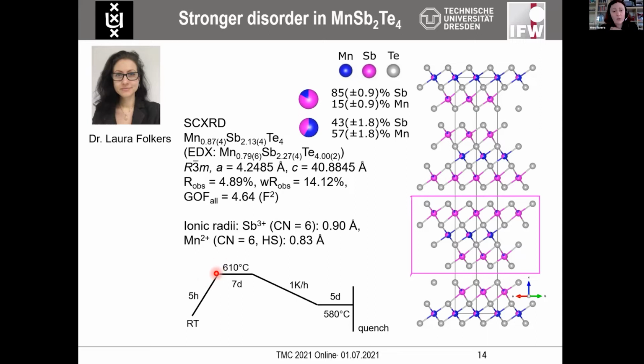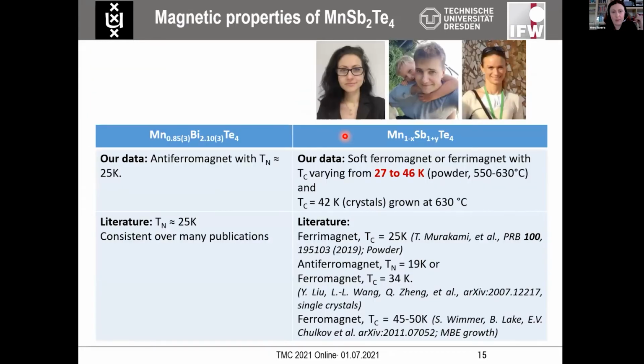So here I'm talking about crystals obtained at 610 degrees centigrade, and as you can see, this is also sub-stoichiometric, so manganese is below 1, and we have intermixing. Those of you who could memorize the percentages in manganese bismuth telluride would notice that here in the outer position, we have 3 times more manganese. And here we have a ratio between antimony and manganese closer to 1:1, while in the bismuth phase, it was more like 1:3 or 1:4. So we have much stronger intermixing.